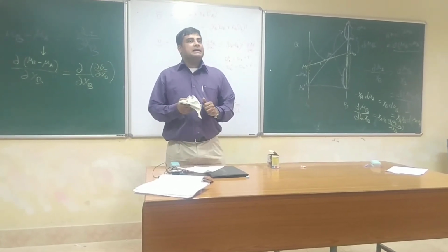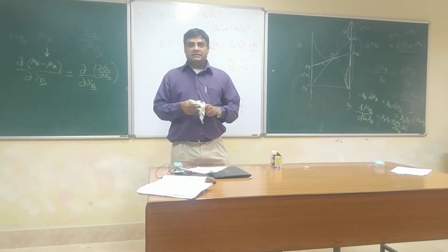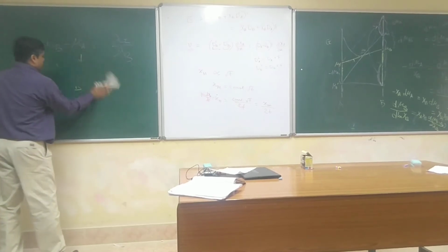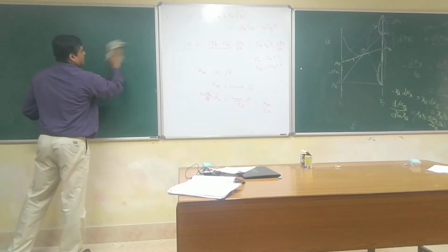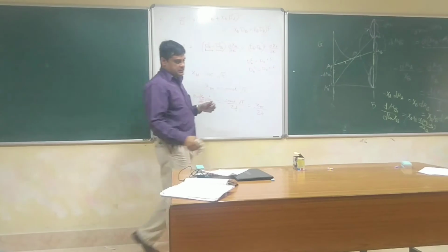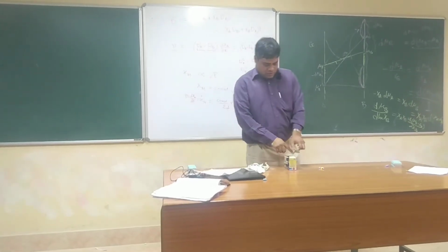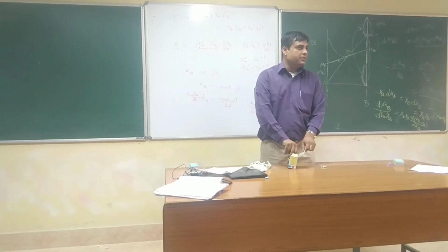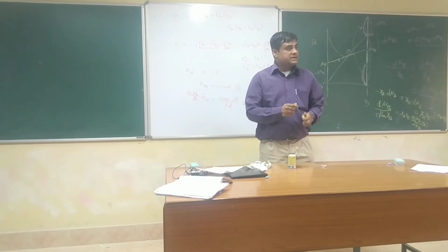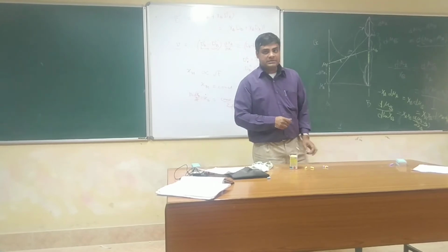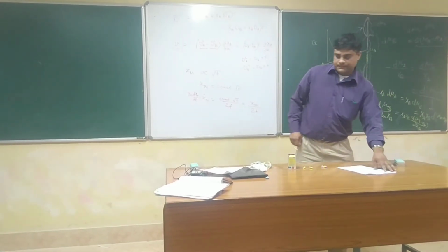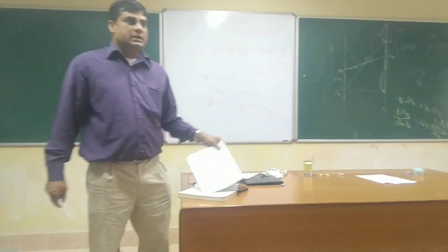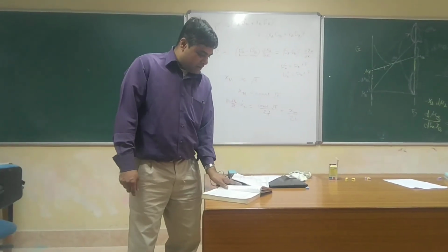If the curvature of the Gibbs free energy versus composition is negative, then your thermodynamic factor becomes negative and your intrinsic diffusion coefficients become negative. In that case, uphill diffusion can occur. For example, spinodal decomposition corresponds to negative curvature, so the thermodynamic factor becomes negative. That's where you see it goes up the hill of the composition.